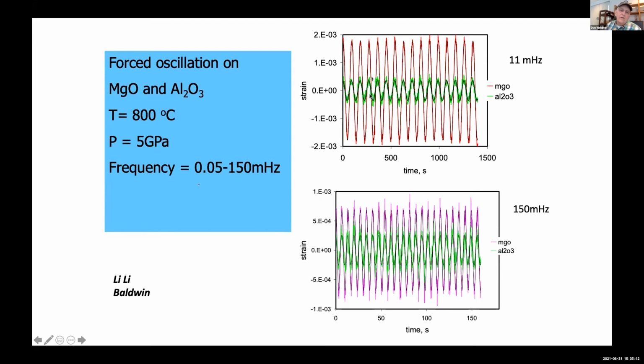And if you look at the red and the green, the ratio of the amplitudes of those should be related to the Young's modulus of the sample if we know the Young's modulus of the corundum. And as the ratio is large, more similar, that means the Young's modulus is more similar. If they're more different, that means the Young's modulus is more different. We can quantify this if we say we know the Young's modulus of the reference.